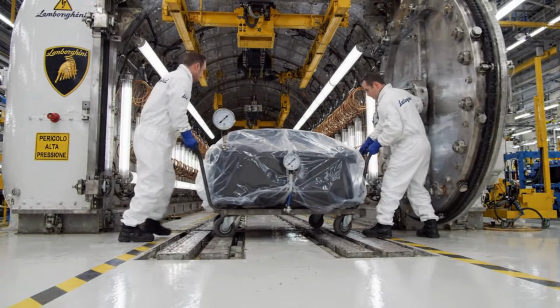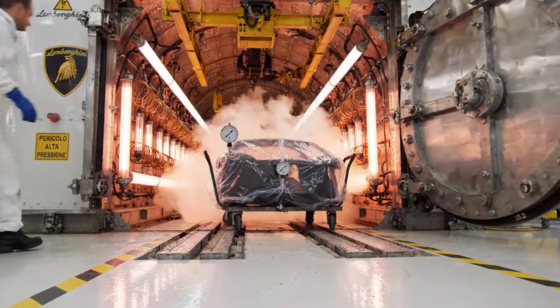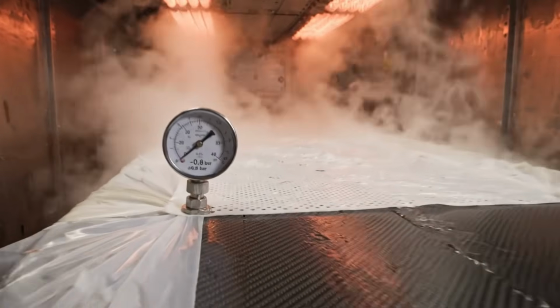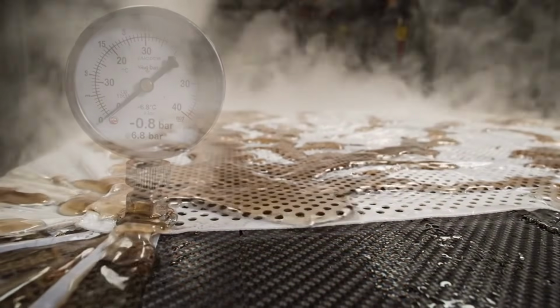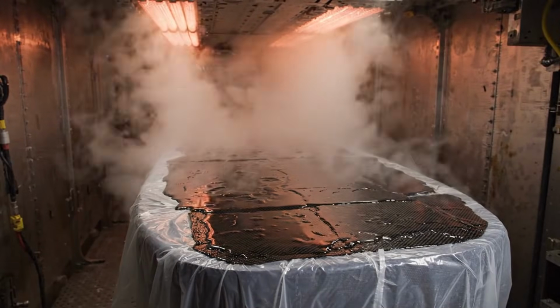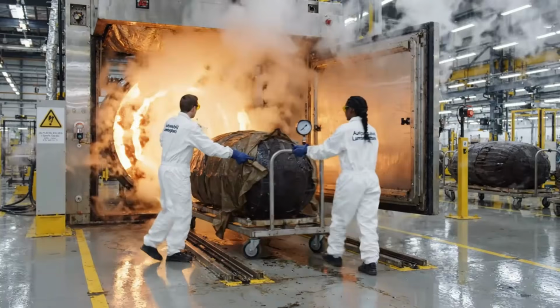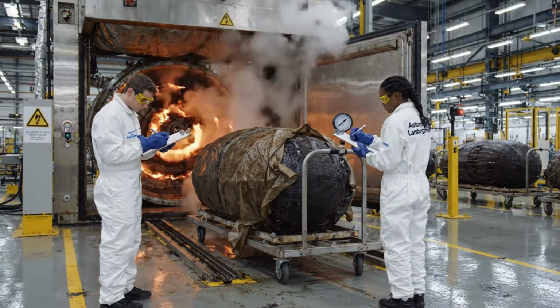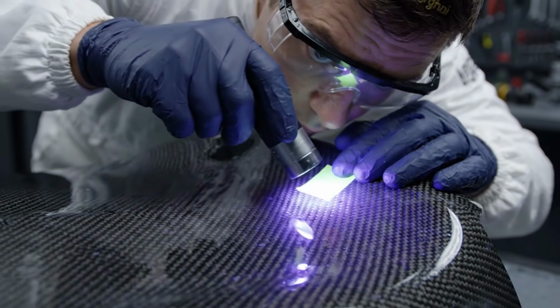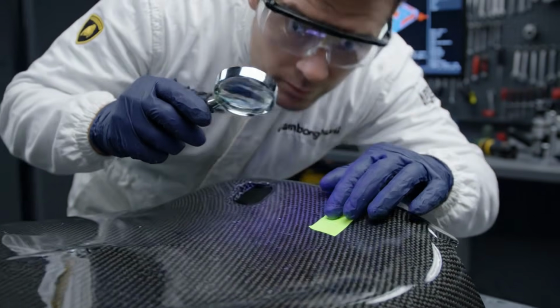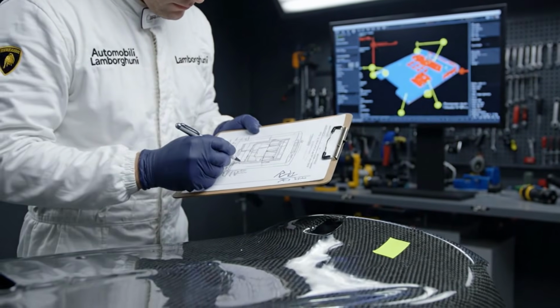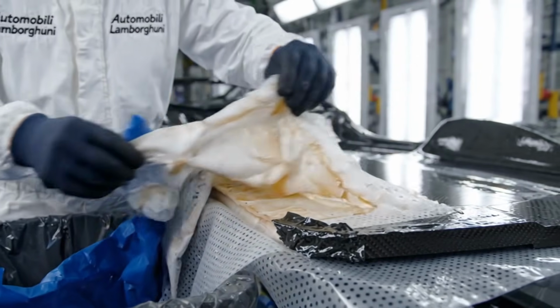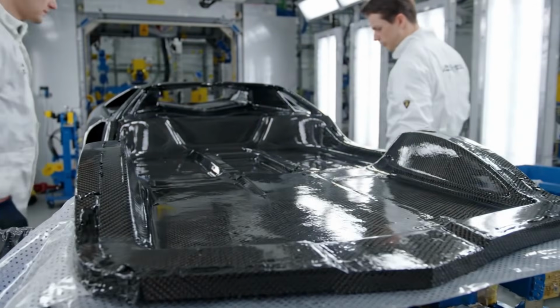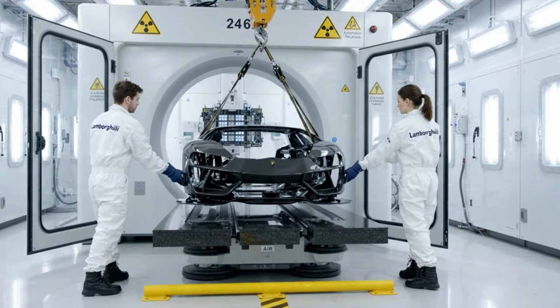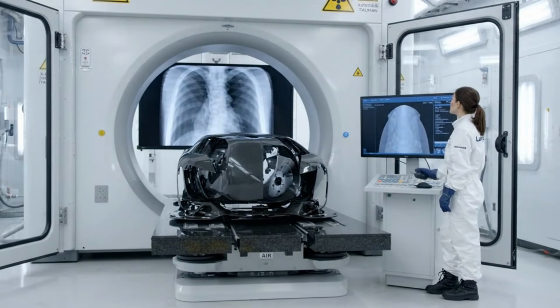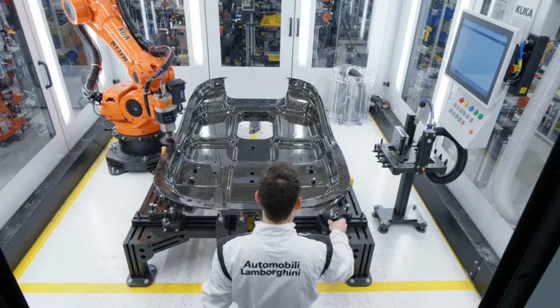The assembled carbon fiber layup is vacuum bagged and loaded into the autoclave, where it will be cured at 135 degrees Celsius. Inside the autoclave at 135 degrees Celsius and 6 bar of pressure, the epoxy resin flows and wets out. After 4 hours in the autoclave, the cured carbon fiber monocoque tub is inspected under ultraviolet light for delamination. The cured monocoque is removed from its mold, the vacuum bagging materials stripped away to reveal a structure. The monocoque undergoes CT scanning for internal void detection, the X-ray reconstruction revealing the internal structure.